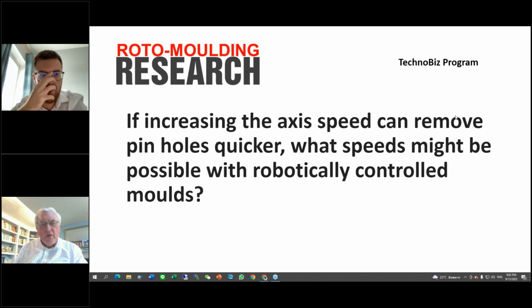I think on that particular question, though, I might be wrong, but my understanding is it's not the rotation speed that is removing the pinholes or the air bubbles. It's the fact that by using a higher rotation speed, you get less air bubbles in the first place. I have a funny feeling that he was going down the route of spinning. I think one of the pictures was at 300 rotations per minute, and he was starting to take into account centrifugal forces or centripetal forces, something along those lines. I think that's where his thinking was going, but I think you're right that the lower speeds, and indeed 60 rotations per minute, is nowhere near 300. Yeah. It probably is more of a heating control process than a force control process.